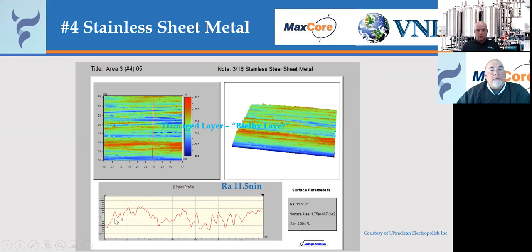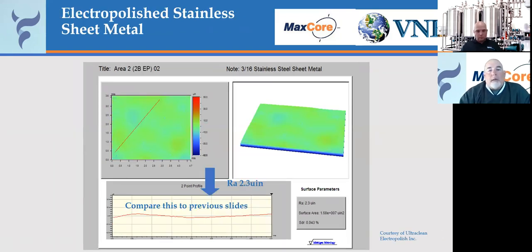So if you look at that, you stop and think about the peaks and the valleys at these particular locations, you're talking about a lot of surface area going up and down and up and down across the surface of that steel. This is the same white light interferometric analysis after an electropolished surface. This is a 2BEP. You can see how much smoother that is across the surface.